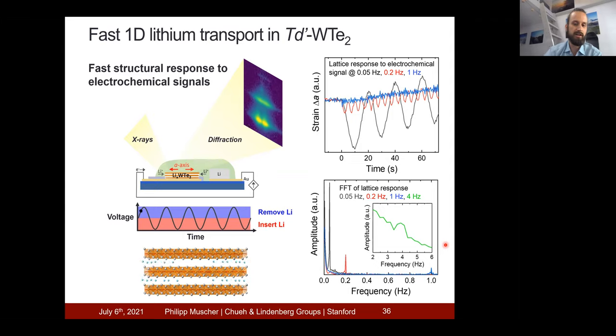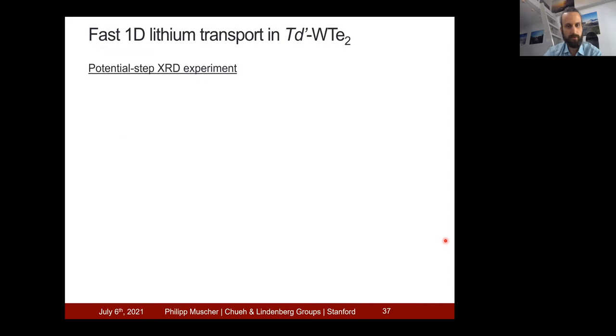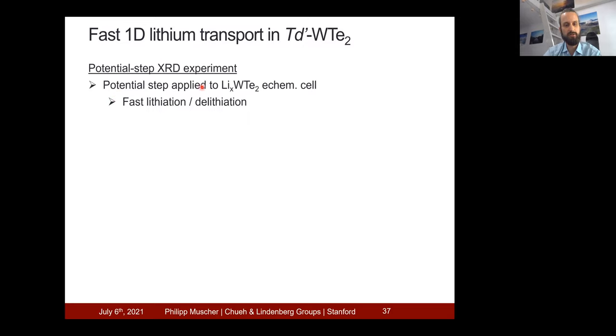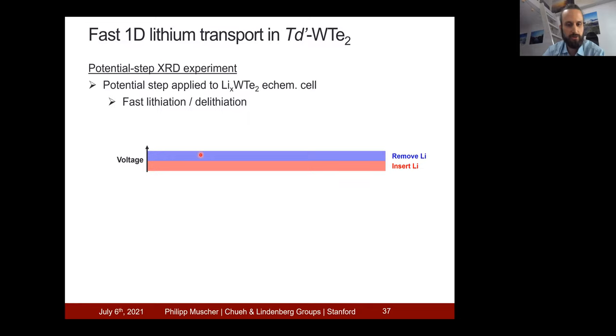So I wanted to quantify the transport properties a little bit further. For this, I turn to a potential step measurement. Instead of the sinusoidal voltage change, I will use a potential step, and this will cause fast lithiation or fast delithiation. Again, we have the voltage shown over here, and there will be a range of voltages where lithium is removed and a range of voltages where lithium is inserted. The potential profile that we choose is one where lithium is going out of the system, so lithium is completely depleted. And then we step to a voltage where lithium gets inserted. And then we look at how the structure is evolving over time.